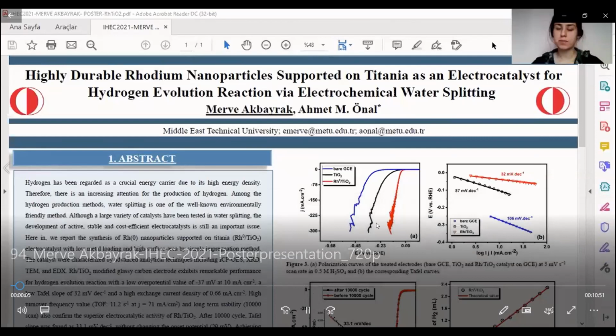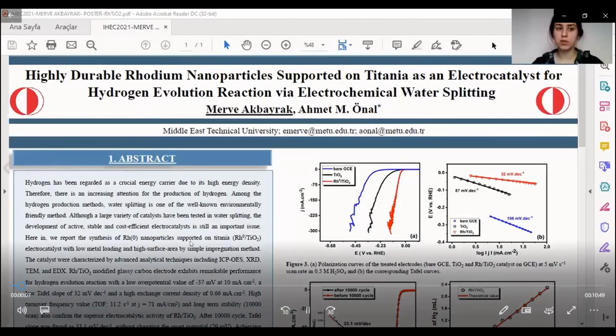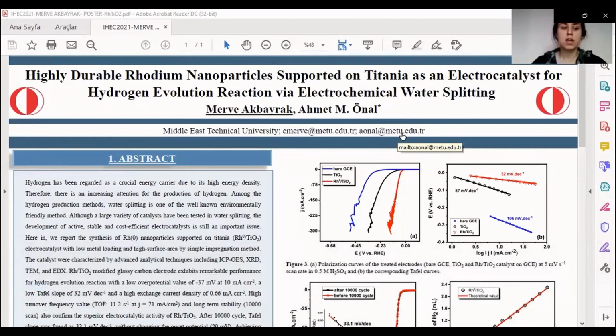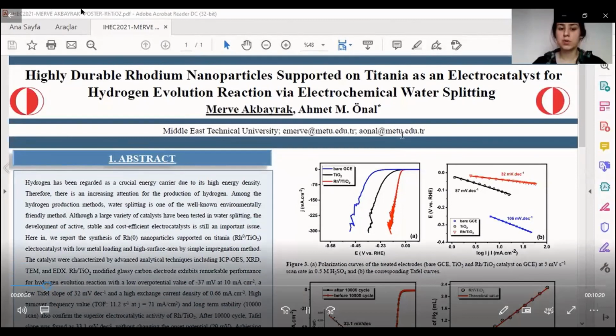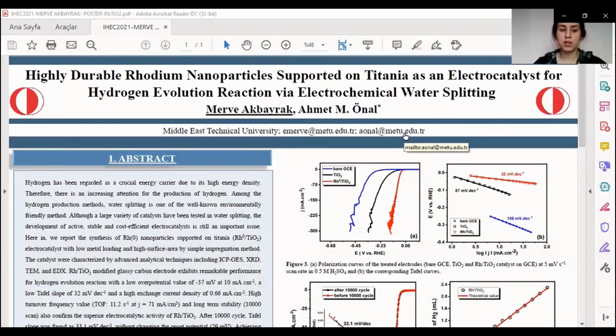Yes, okay. Today I'm going to present a highly durable rhodium nanoparticle supported on titania as an electrocatalyst for hydrogen evolution reaction via electrochemical water splitting. In this study, the preparation, characterization, and investigation of electrocatalytic activity of rhodium titania towards the hydrogen evolution reaction are presented. After impregnation and reduction of rhodium-3 ions on the titania surface, according to the ICP-OES analysis, the rhodium metal content of rhodium titania was determined as 0.5% weight. Rhodium titania was also analyzed by transmission electron microscopy, TEM-EDX, and X-ray diffraction analysis.